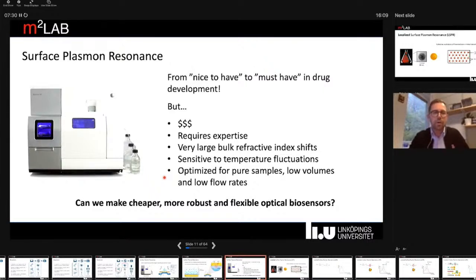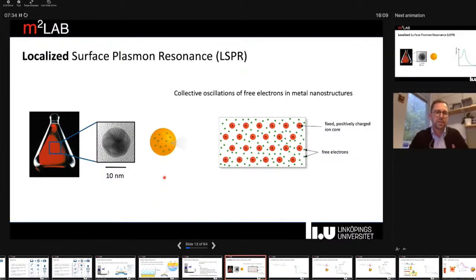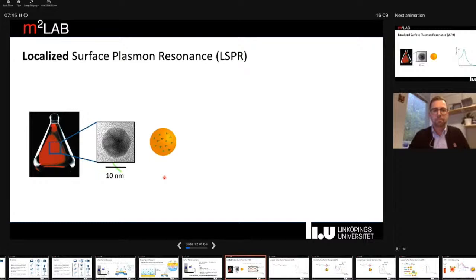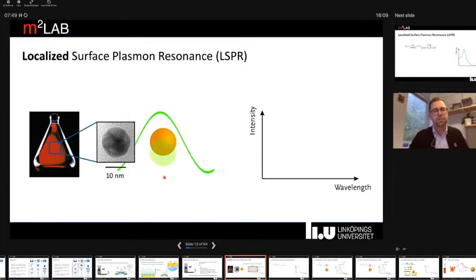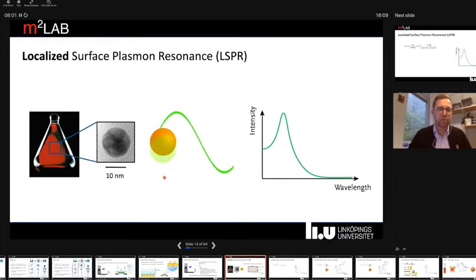And this made us look into the field of localized surface plasmon resonance. So essentially a very related phenomenon to SPR, using metal nanostructures instead. When having metal particles that are small in size, and small in size typically means less than 100 nanometers, then we can much more easily induce collective electron oscillations. Essentially, we don't need any complicated optical setup to do this. So we can just irradiate the particles and we induce these collective electron oscillations, which results then in a lot of absorption of the visible light, as well as scattering. And we can see this as a quite pronounced extinction band in the visible wavelength range.